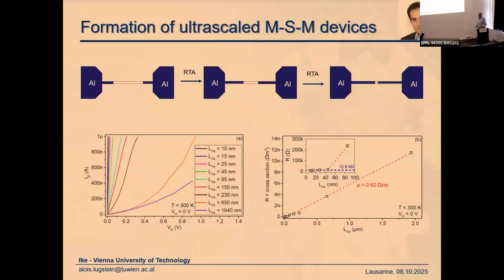And Maciej Sistani made use of this and made devices of different segment lengths and did a very simple experiment. Namely, he measured the IV characteristic of these devices with different lengths and varied the channel from about 2 microns down to 10 nanometer. And thereof, he calculated the resistivity, just the inverse of the slope, plotted this resistivity as a function of the segment length.